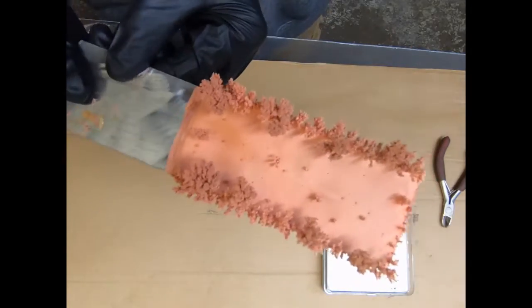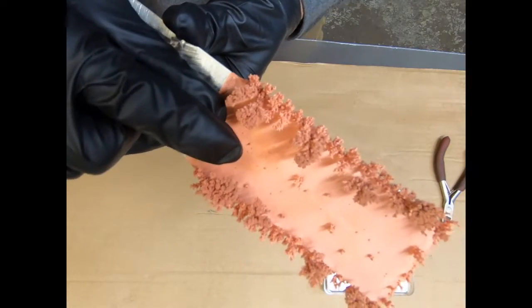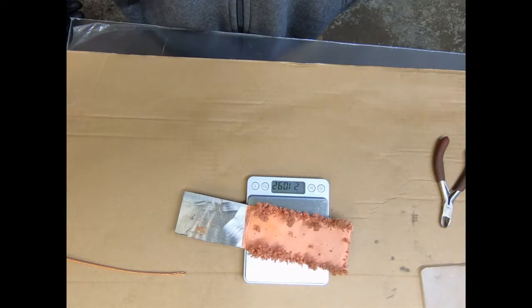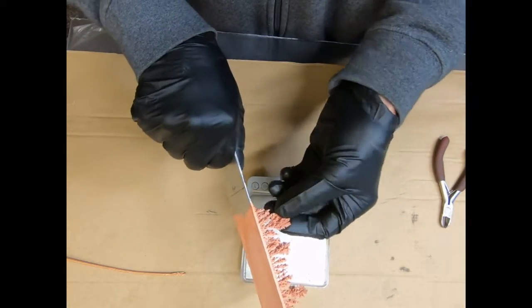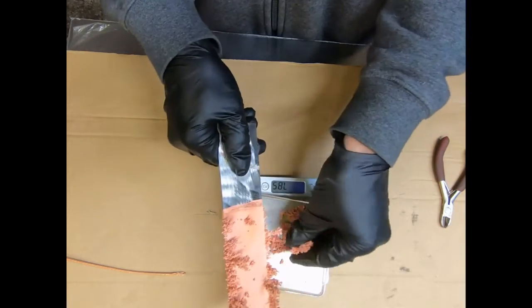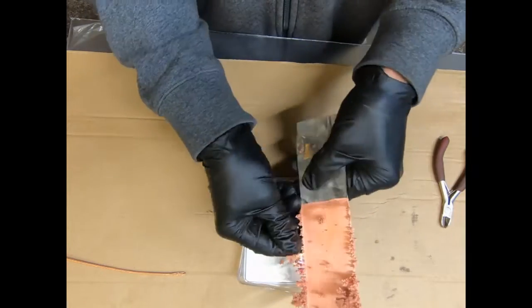Last time I touched them they're quite strong — I'd hate to break one off. I'm about to weigh this thing but just for the sake of it we'll tear off this little middle one. That is 260.12 grams with all that copper on it. I'm going to try and tear some of these crystals off — they are very tough and do not break off easily. You could have very high turbulent flow in a cell with copper and wouldn't have to worry about busting these crystals off.